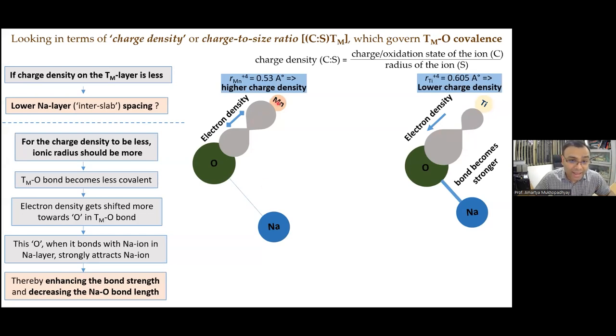So by varying the covalency of the transition metal-oxygen bond, one can vary the effective negative charge on the oxygen ion. And now let me take back my previous statement that nothing can be done to this bond. Because if we can vary the effective negative charge on the oxygen ion, we can alter the length and the strength of this bond, the sodium-oxygen bond. And that is where the entire field lies: how to manipulate or modify the air-water stability, the structural transformations during desodiation and sodiation, and even change the sodium content of the P2-type structure. And that is what we will see today in this talk.